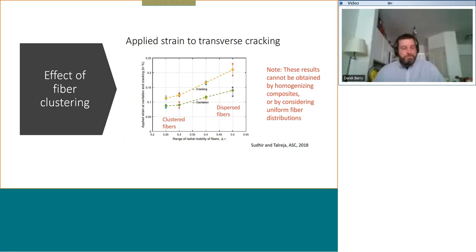So it's like describing the cooking by just talking about it and then showing the final product. So through a lot of development that we have done, the type of results that we get out from this analysis is how the failure is going to be depending upon the defect severity of the composite structure. In this graph, you see on the horizontal scale some defect severity in terms of the mobility of fibers as you are doing processing. On the vertical axis, you see the applied level of loading at which first failure occurs. And then you see in the clustered fiber case, you start failure much earlier than when you had dispersed fibers case. And these are quantitative results that match the experimental data. Let's go to the next slide, please.